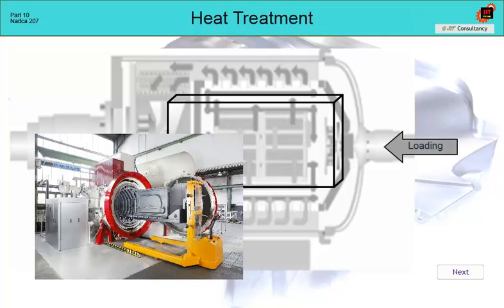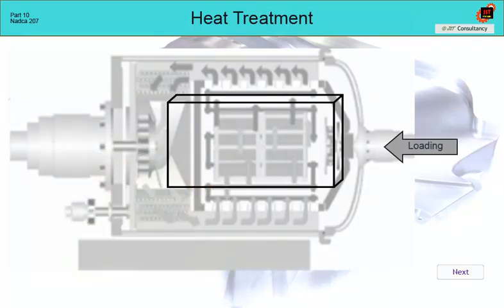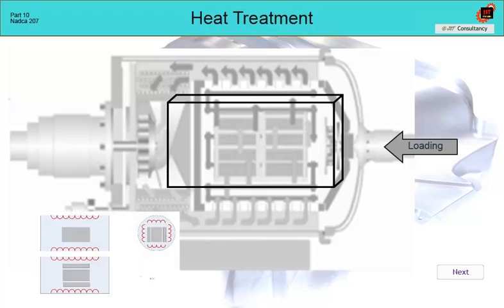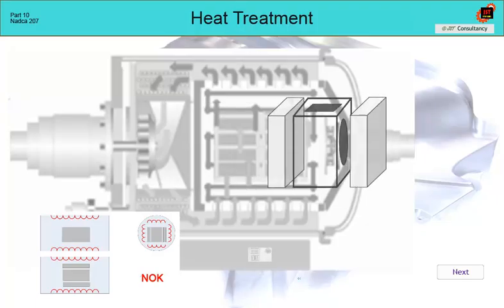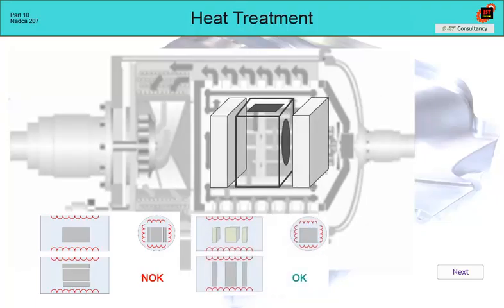In the case of installing multiple inserts, the situation is different. If we placed all the inserts as in the previous case, some of them would not be irradiated at all, because they would be shielded by inserts located near the heating. Therefore, the only possible solution is to place all the inserts perpendicular to the furnace axis. This will ensure that the inserts will be evenly separated, and their heating will therefore be similar.